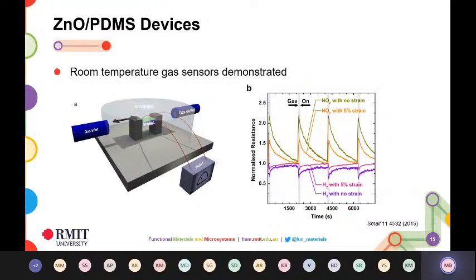They are quite versatile. The fact that zinc oxide is a very versatile oxide allows us to demonstrate quite a few different applications. What you can see in this particular case are gas sensors, which are capable of operating at room temperature, which is quite rare. And you can see zinc oxide is sensitive to both nitrogen dioxide and hydrogen. With strain, you're not really losing much of the performance. So that's a nice room temperature demonstration of gas sensing using these devices.